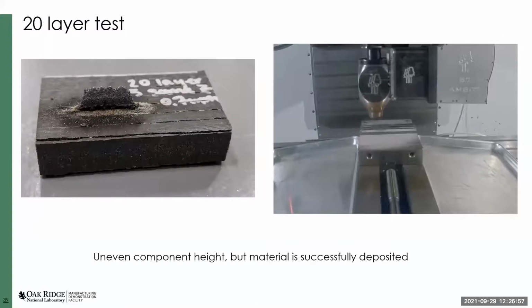There we go. And then another test that I did with the carbon fiber ABS was just to see what happens when you try and stack multiple layers. So up to this point, I've been looking at the short-term effects of the DED process on the polymer, basically determining whether or not the polymer will survive being exposed to a laser at 100 watts and being exposed to molten metal. So what will the polymer do on the order of microseconds to milliseconds in response to this process?